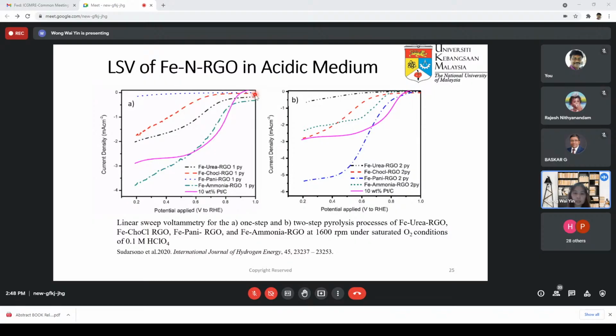How we determine the activity of the ORR of a catalyst is based on the onset potential. The higher, the more positive the onset potential, the more active it is. So the Pt/C is still, inevitably, higher as compared to the rest. For first step pyrolysis, ammonia shows the highest activity compared to the rest.